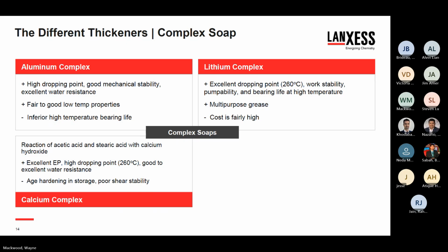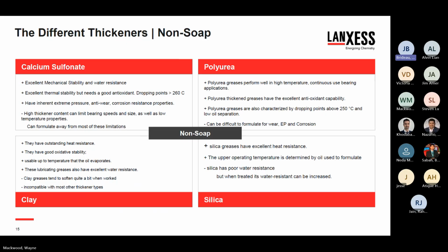On the non-soap side, I'll come back to the calcium sulfonate. We'll start with the clay. Very good heat resistance. They're good in oxidative stability because of that clay structure. There really isn't anything to melt or to oxidize at the temperatures anybody might operate these under. Really, the upper operating temperature is the point at which the oil begins to evaporate. They have good water resistance. Their mechanical stability can be a bit suspect, and they are essentially incompatible with most other thickener types. Just the way their structure is put together, they get disrupted quite easily.